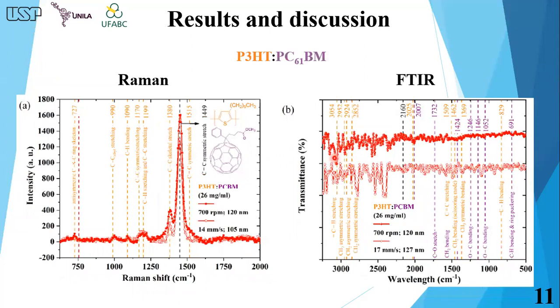P3HT:PCBM dissolved in dichlorobenzene with a weight ratio of 1:1 and a concentration of 26 milligrams per milliliter were deposited by two techniques, showing that for the films, except for the intensity that decreased along with the thickness, the chemical structure is preserved.